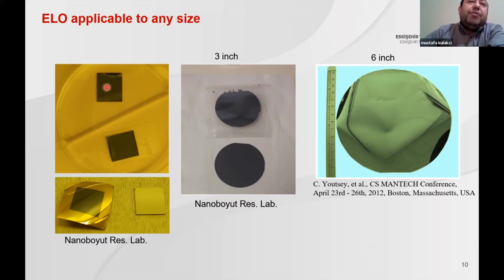The left-hand side, these belong to us. One of them is a laminated structure on the PET carrier. The other is attachment to the flexible polyimide by using gold fusion techniques. Here you see this is again from our labs. Full 3-inch solar cell structure is lifted up from substrate onto the PET carrier.